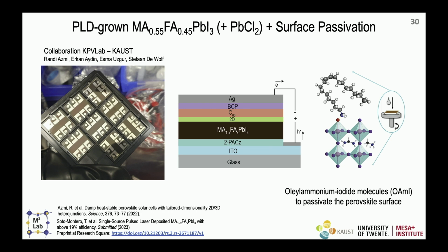So for this, we actually collaborated with the group in KAUST, Stefan de Wolf, where they developed this very nice surface passivation based on OAMI molecules. So these are molecules just spin-coated on top of the surface of the 3D perovskite, and forms a 2D perovskite layer on top. So now we have the perovskite and a 2D layer on top. And it actually works in our case. We prove we have the 2D perovskite.